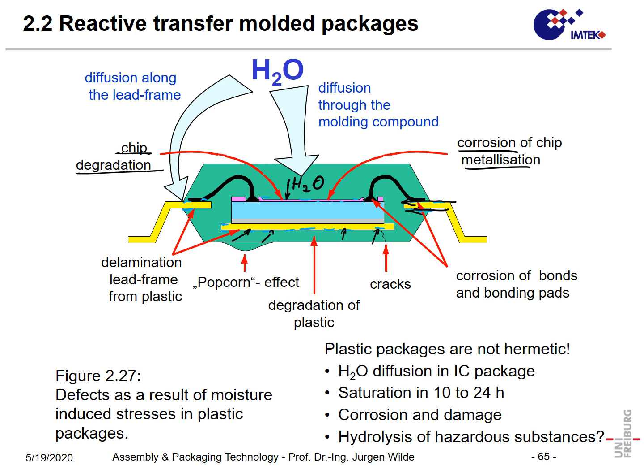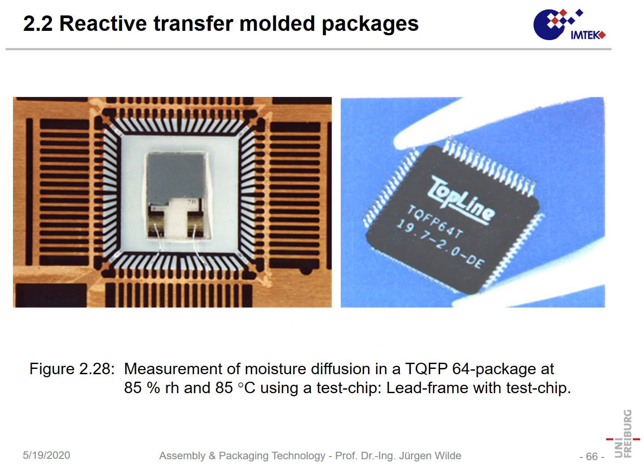But there is another effect which can be very detrimental, and that's so-called popcorning. Popcorning appears when we go into a soldering process, and what's the typical temperature of soldering? It's around 250 degrees centigrade, and that will have a strong effect on the water. But first, let's have a look to see how fast water goes into such a package.